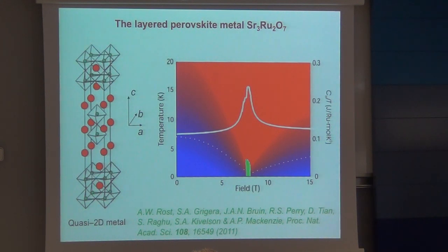Sorry, yeah. The Fermi surface on both sides? The Fermi surface is measured on both sides. It's different because, just in the same way that a ferromagnet at its TC will polarize its Fermi surface into a different spin up and spin down one, that's what happens in metamagnets as well. You have a field-induced Fermi surface polarization, and that can be seen. But it's all metal everywhere. We can even see quantum oscillations in the anomalous phase. So there's no question that these are all metal-metal transitions.